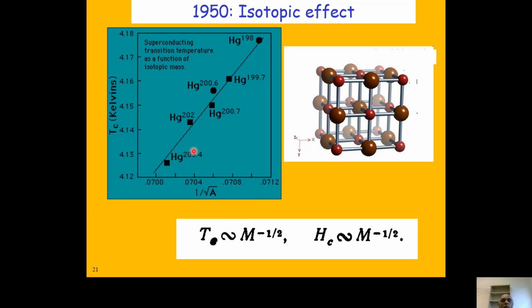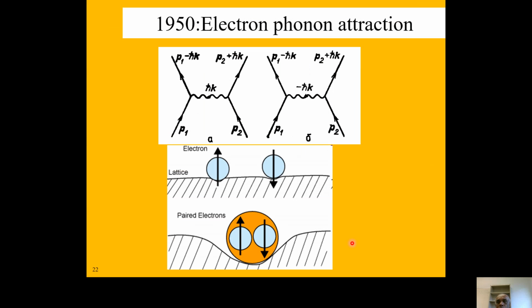So that's how this works. If you plot 1 over square root of m, the atomic mass, versus Tc, they show linear behavior. Also, the critical field goes like 1 over square root of m. This was the isotope effect, basically changing the number of neutrons in the system. Then in 1950, they tried to understand this Cooper pair situation.